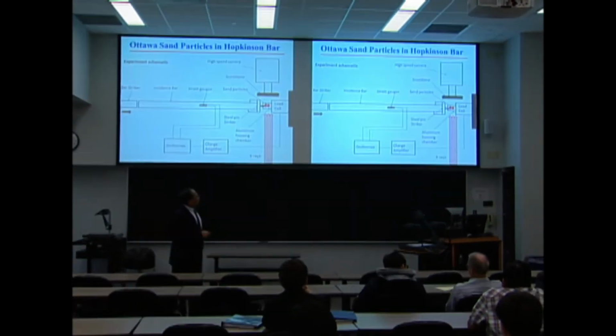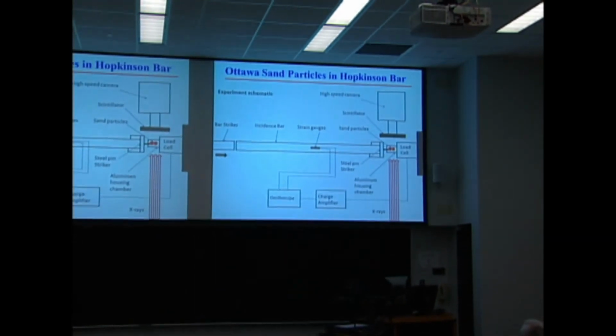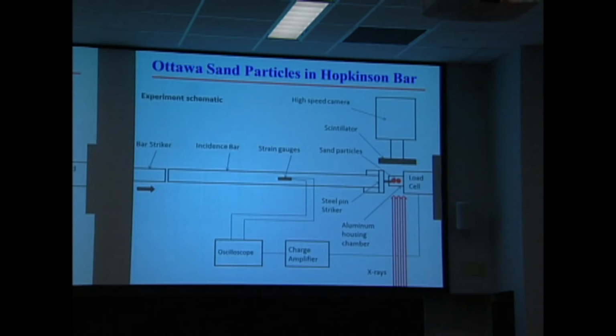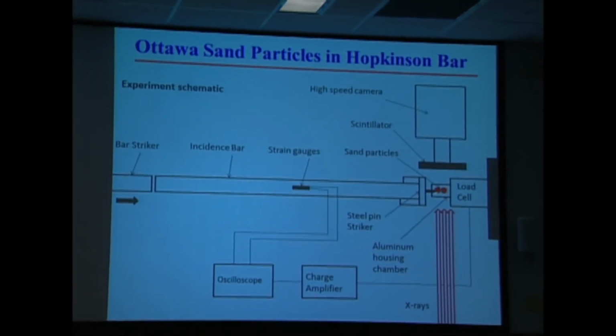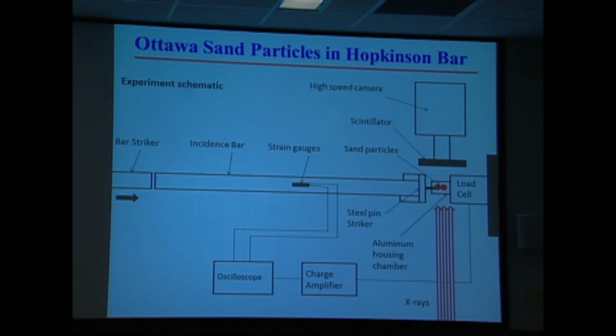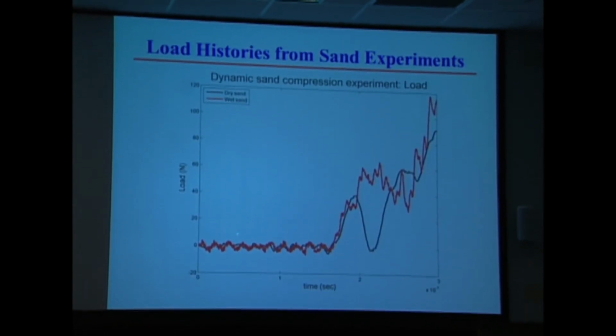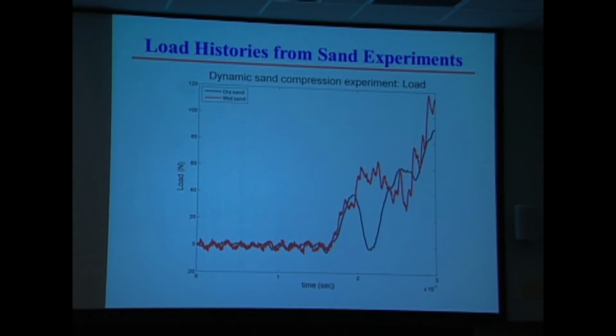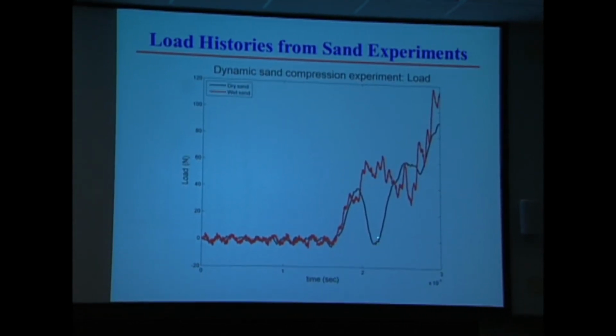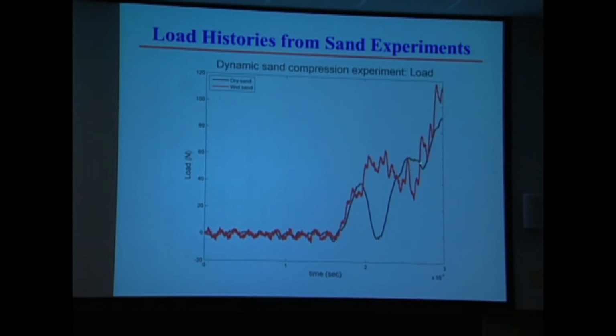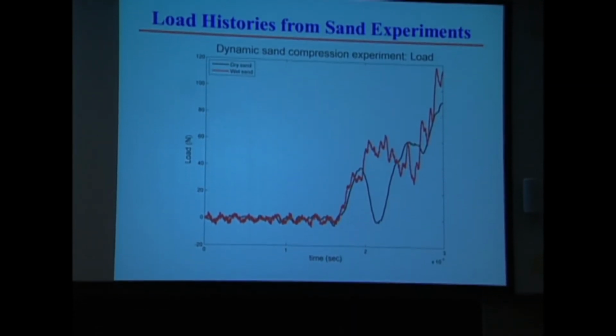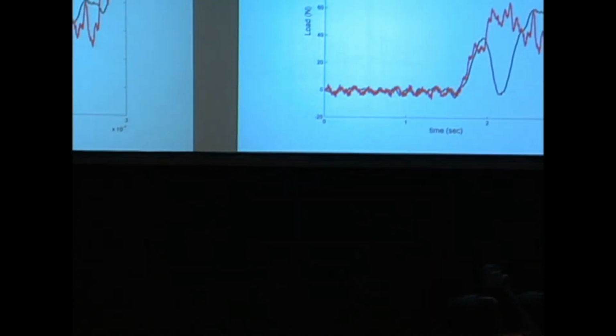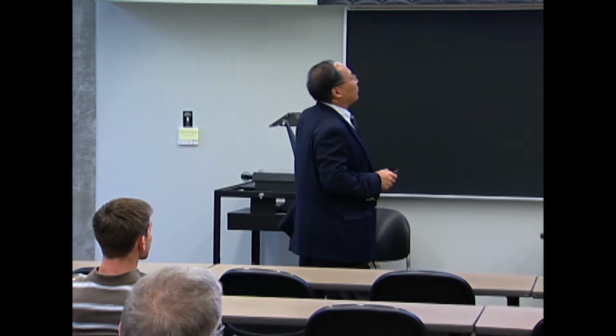This one, we put 2 sand grains next to each other and use the bar to impact the grain and look at how the grain breaks. So that's a very fundamental mechanics issue. And we can measure the loading history, that as the grain breaks, the first one breaks, then reload back, the second one breaks at a higher load. If you fill the tube with water, then the loading history is a little different, but I'm not going to talk about this wet issue. We're going to show you the dry grain results.